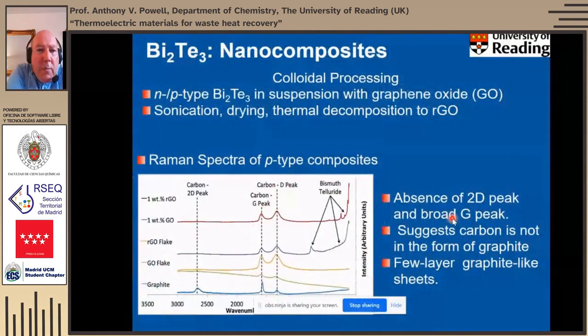So this is some work that we've done very recently. We've not yet even published it, on nanocomposites of bismuth telluride. So this is trying to take the current state-of-the-art material at low temperatures and try to improve it. We've done a colloidal processing route where we essentially mix the bismuth telluride with known amounts of graphene oxide. And after some treatment, we do some decomposition of that graphene oxide to reduced graphene oxide. So we introduce essentially a carbonaceous phase that's well distributed throughout our bismuth telluride.